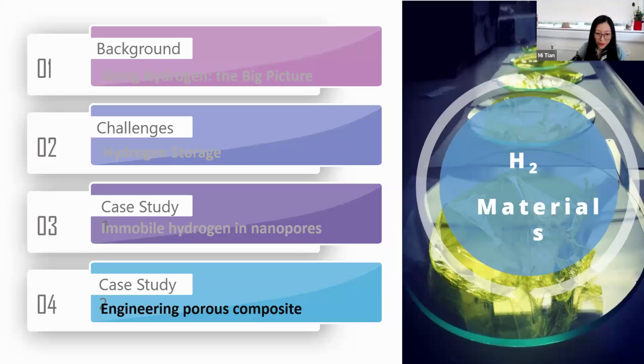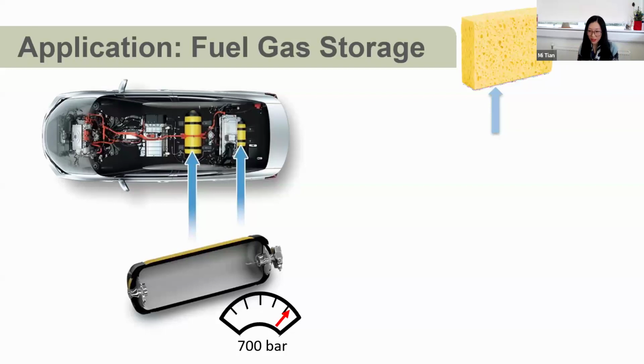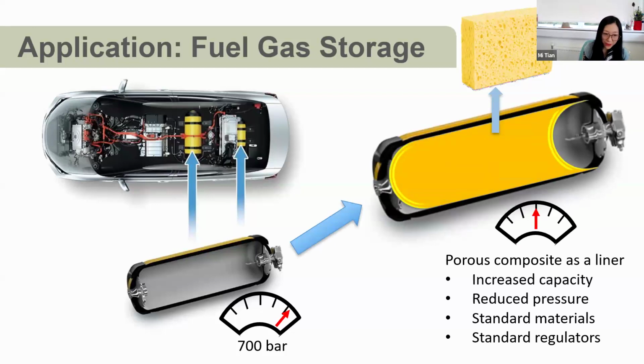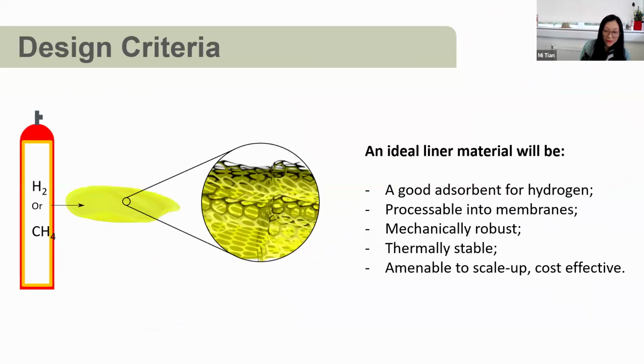So we achieved success in this theoretical study, and we know the optimal pore structure for hydrogen storage. Based on that, we decided to engineer our material for a new generation hydrogen storage tank. We want to have a liner inside the high pressure hydrogen storage tank using our porous composite in order to either increase the hydrogen capacity or reduce its pressure. Therefore, we can use more standard material and standard regulator, reduce the cost and improve the safety.